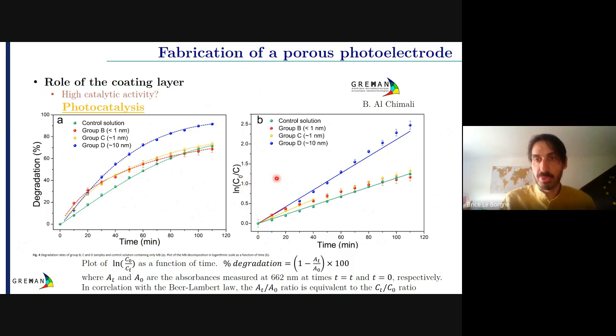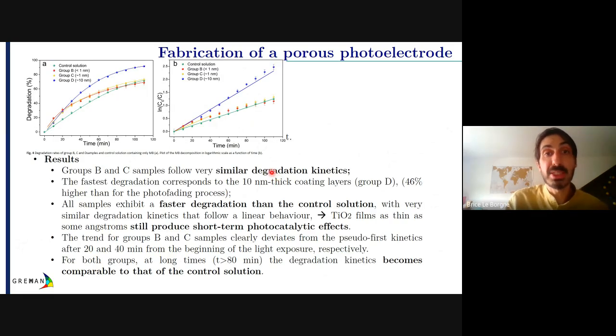So this is the detail on how to calculate the degradation as a function of the concentration of the solution, right? We can discuss the details if needed, but it's very common in the field. So basically, we can see that for the 1 nanometer or less layers, we have similar degradation kinetics, which is interesting. But of course, after some time, the control solution reaches the same degradation point. This means that after some time, for the thinnest layer, you have saturated all the photocatalytic sites, so you don't really do anything anymore. While for the 10 nanometers, very efficient and much faster. Okay, I wouldn't say very efficient because, of course, compared to proper catalysts, it's not great, but still, it's interesting to see that thanks to the porosity and the titanium dioxide, it worked.